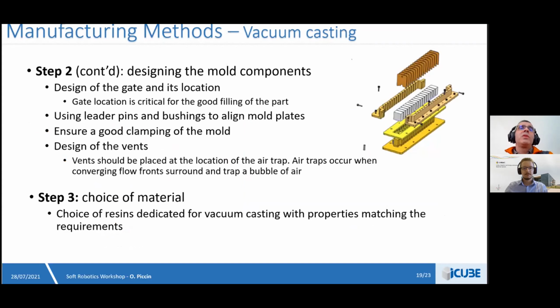When you are designing the mold, an important element is the position of the gate. This is for the good filling of the mold. And here you can see different elements, such as a good location for the different parts of the mold, a good clamping of the mold. And also an important point is the placement of vents to avoid air entrapment in the mold, to avoid bubbles in the system.